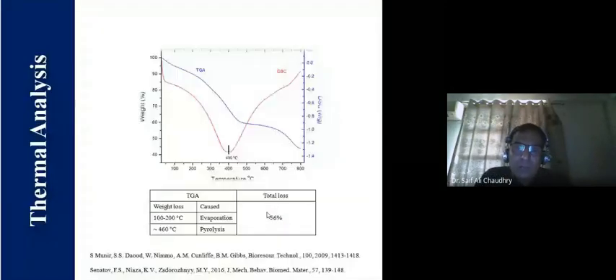Now the nanocomposite material was characterized through the TGA thermogram, and it indicates that during 100 to 200 degrees Celsius, evaporation was there. Evaporation means water evaporation, and the volatile organic compounds available in the black cumin were evaporated during this. Now around 460 onward, it was pyrolysis. Only 56% of the total weight got lost. It means only 44% was oxide component. Oxides are very stable, therefore they were there, and 56% of the organic material has gone away.